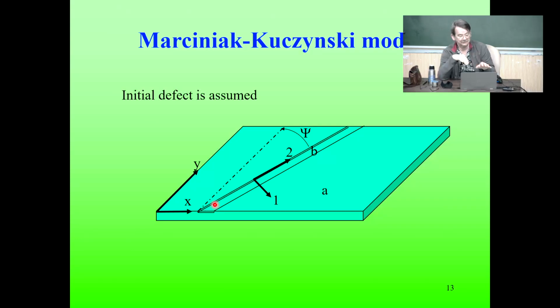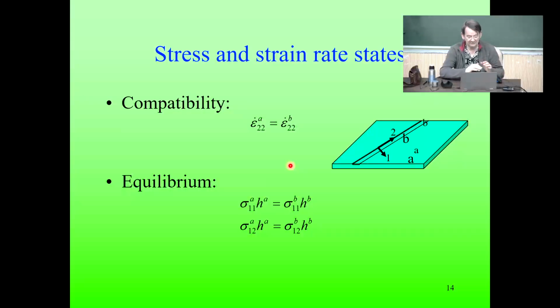So we have to follow the deformation actually in the two zones. In zone A, which is the matrix in the big sheet, and zone B, which is the groove. We write some basic equations. The main compatibility equation is that the strain component in direction 2 in the groove, epsilon 2 B, has to be equal to the strain in the matrix. The groove keeps its length. That's a constraint. It is always within the sheet.